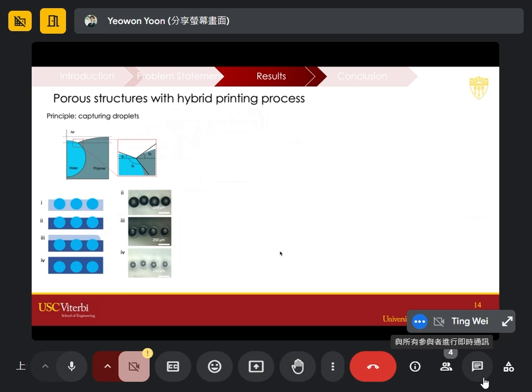We have liquid resin, and this liquid resin is immiscible with water, meaning they're like oil and water that do not mix together. So when we dispense water on top of liquid polymer, it basically floats up to the surface because of the lighter density of water. And when that happens, we cure it with UV light. So everything is solidified, including the polymer that's surrounding the water. Then we tried to apply another resin on top of it to make sure this structure can contain water even with another layer on top of it. And we found out, as you can see in the bottom right figure, that all the water droplets are actually captured inside the polymer.